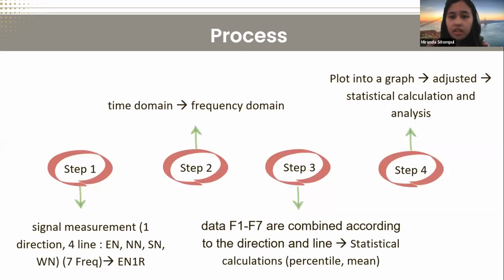The process is, first, the signal is measured using a horn antenna, and then frequency signal measurements are carried out in 4 different measurement directions, namely EN, east direction north line, NN, north direction north line, SN, south direction north line, and WN, west direction north line, and at a radius of 1 kilometer until 3 kilometers. The frequency captured by this antenna is the frequency of 680 megahertz until 18 gigahertz, which is then divided into 7 parts, namely F1 until F7.